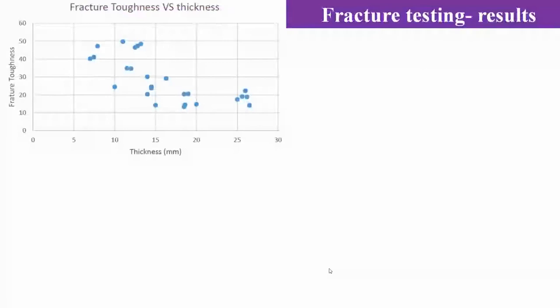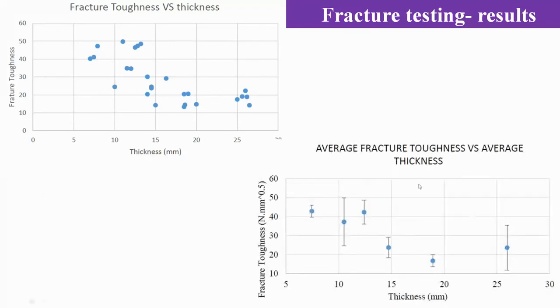To ensure a state of plane strain, to measure the correct value for the mode 1 fracture toughness of polyester, fracture tests at different thicknesses were performed. As you see, fracture toughness versus thickness for SENB specimens is shown. On the right, you see the average values of fracture toughness with standard deviation, which shows a minimal thickness of 15 mm is required to ensure the state of plane strain.